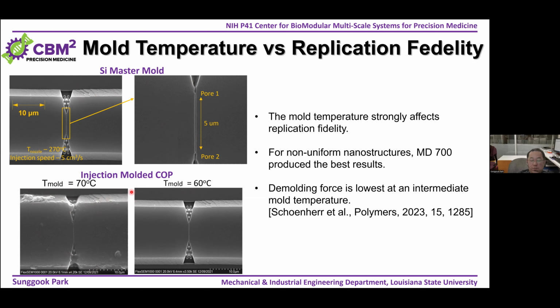I just tried to see what happens, and actually there is a recent report that the demolding force is lowest at an intermediate mold temperature. When you demold at a very low temperature, you have very high thermal stress, while if you demold at a high temperature, you have more adhesion. So there is an optimum demolding temperature between the low and high temperatures, and this is what we see in these experiments. Even though a higher mold temperature is good for filling of polymer melt into mold cavities, that is not always good for the demolding characteristics. So you have to optimize the process to develop nanoscale injection molding.